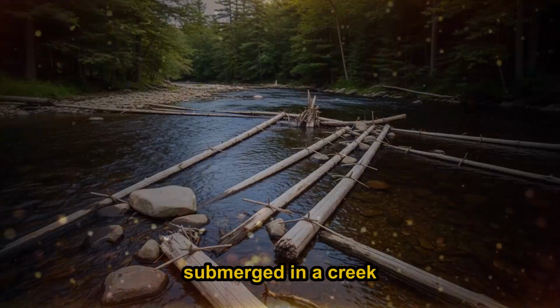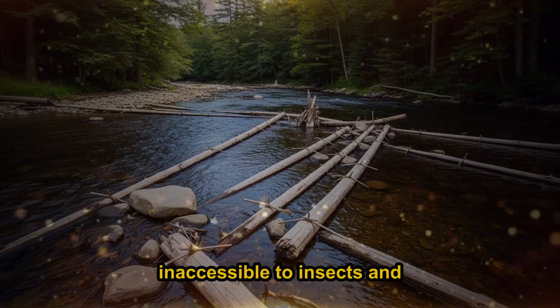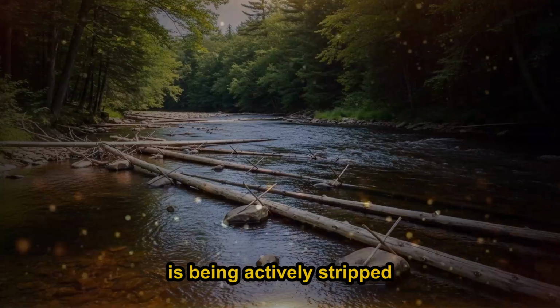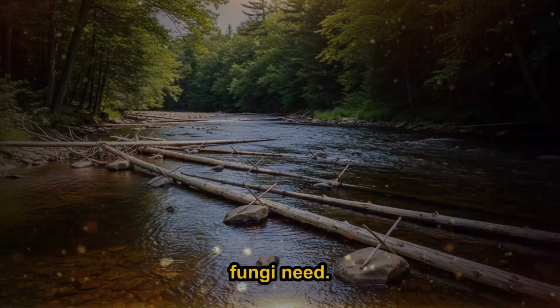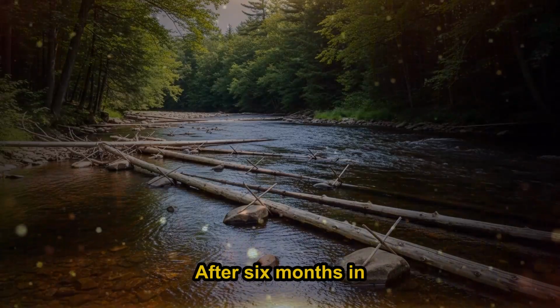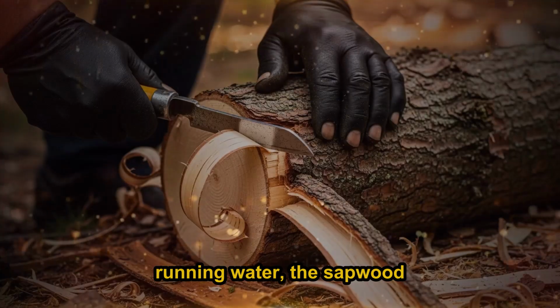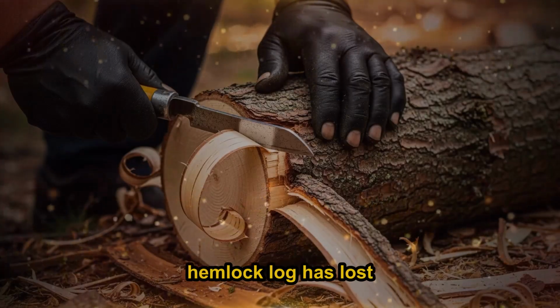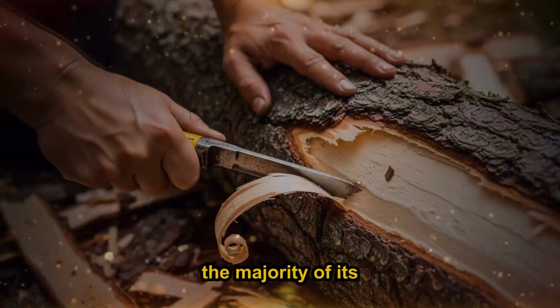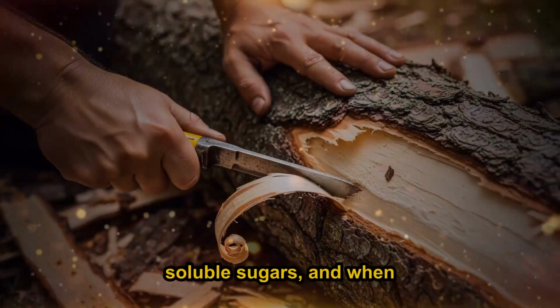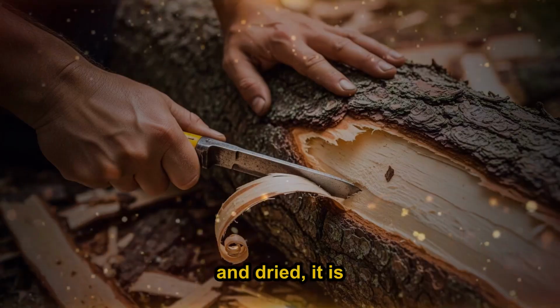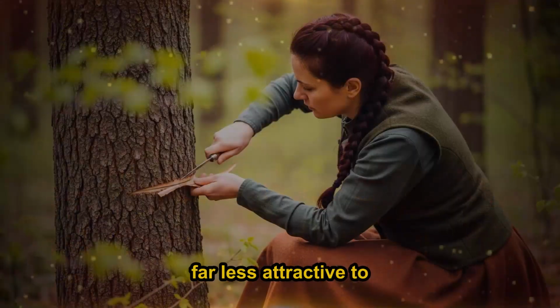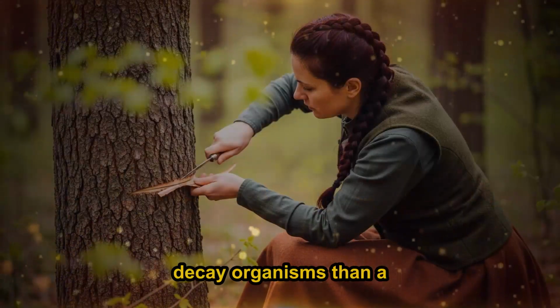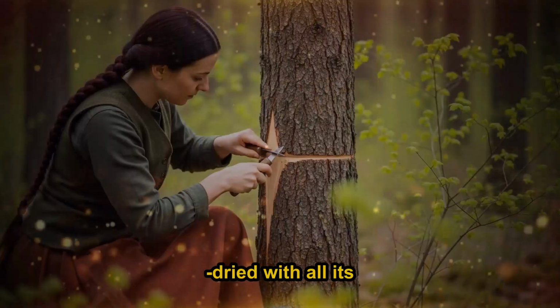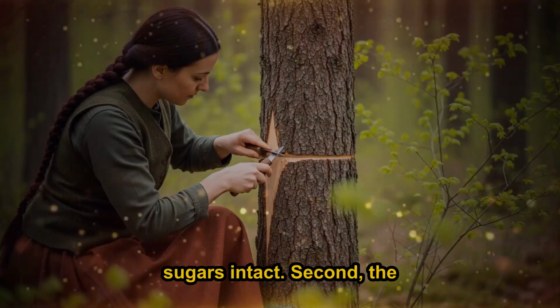A log submerged in a creek is inaccessible to insects and is being actively stripped of the nutrients that fungi need. After 6 months in running water, the sapwood of a spruce or hemlock log has lost the majority of its soluble sugars, and when the log is removed and dried, it is far less attractive to biological decay organisms than a log that was air-dried with all its sugars intact.